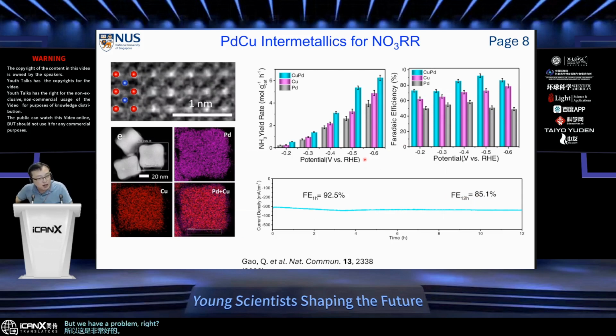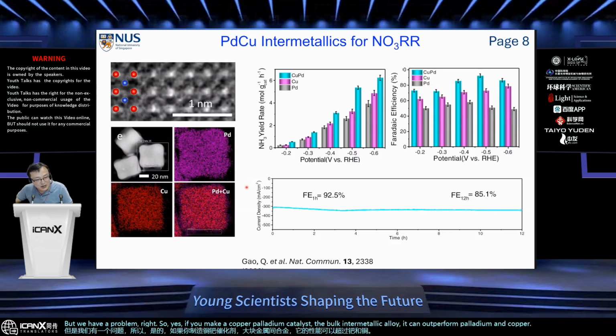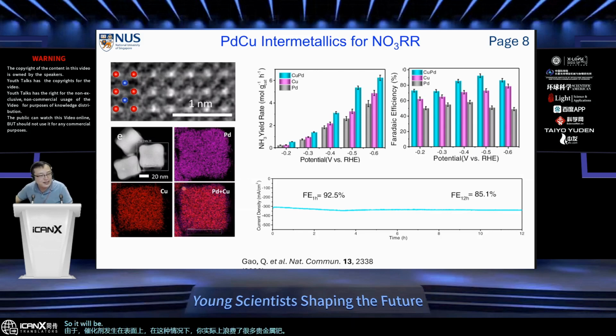So yes, if you make a copper palladium catalyst, the bulk intermetallic alloy, it can outperform palladium and copper. However, since the catalysis happens on the surface, you're effectively wasting a lot of a precious metal, in this case palladium, inside the material. So it will be much nicer if we can just put the precious metal on the top surface, without wasting them inside, right? So this basically becomes the next goal: how to develop a next generation catalyst for this particular reaction.